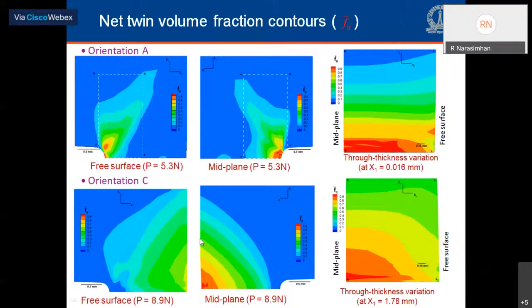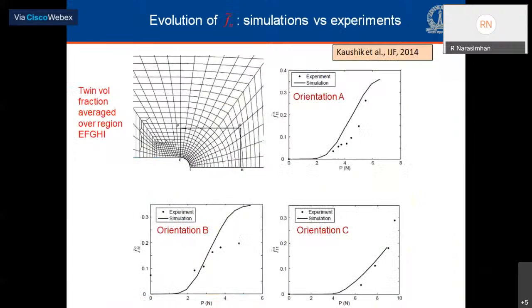On the other hand, if you look at the bottom side, you see a different pattern of twin volume fraction development. It starts at the far edge of the specimen and then approaches the notch root. And there's a region near the notch root which is free of twins, as we saw in the experimental EBSD images. And also there is more distinct thickness dependence, which we can make out clearly on the image on the right side. So therefore, the simulations do capture some of the essential features of what we saw in the experiments.